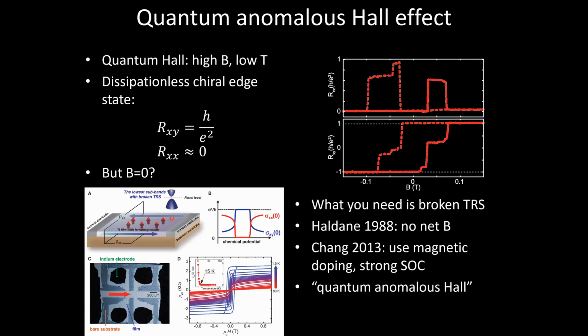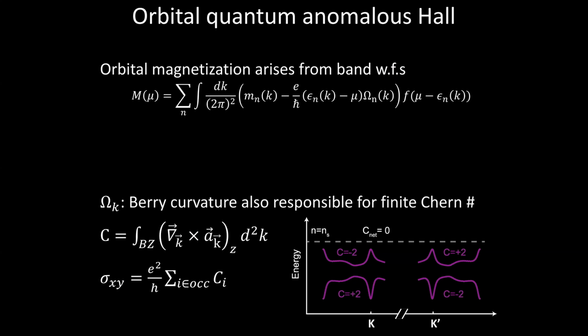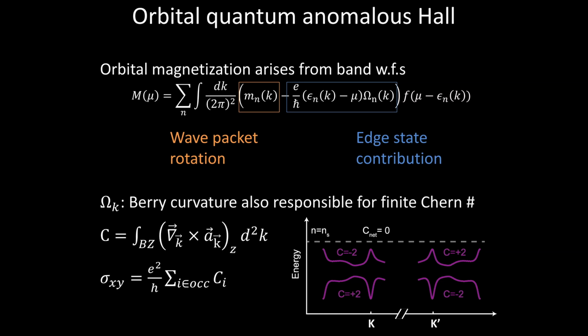It turns out that this system that we study, you can understand actually in a very simple way from just an intrinsic effect. You have these relatively flat bands that come from this high density of states. And if you just ask what is the lowest energy configuration of this system when you put 1 electron per unit cell, it turns out the system just prefers to occupy one of these bands. And these bands have a finite Chern number. It's something you can understand quite well theoretically. It comes from the same Berry curvature that generates these orbital moments, right? And it will just spontaneously magnetize. Okay.